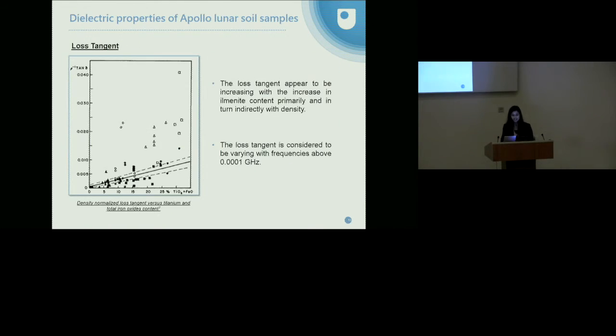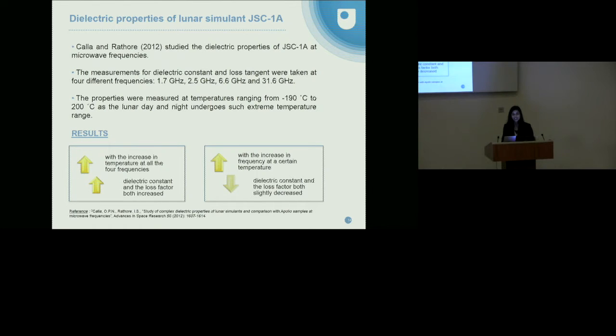When they looked at the loss tangent, they found that the loss tangent appeared to be primarily increasing with the ilmenite content and secondarily with density. They commented the loss tangent is considered to be varying with frequencies above 0.0001 gigahertz, but not much analysis was done. Another work carried out by Calla and Rathore talked about the dielectric properties of JSC1A, the lunar simulant, at 4 different microwave frequencies: 1.7, 2.5, 6.6, and 31.6 gigahertz.